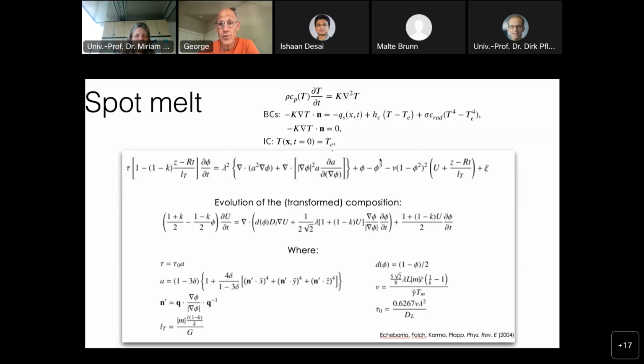There is a nonlinear advection term. There are penalty terms from the phase field in order to have a 0 or a -1, 1 penalization to indicate solid or liquid. Plus additional terms that have the temperature. It also has this C variable here, which is essentially a random variable. So this is in fact a stochastic partial differential equation, and this term is required in order to trigger dendrite formation. So the problem is very challenging, and also the initial conditions, as I said, have the initial grain distribution. So it's a stochastic differential equation with random initial conditions.